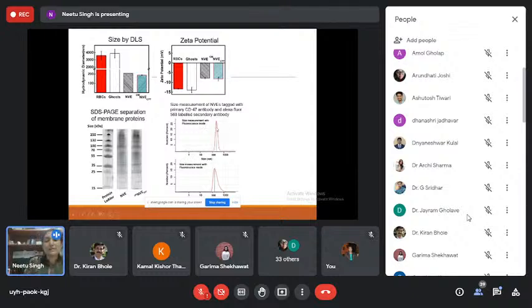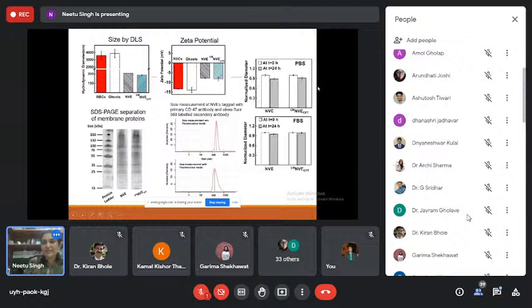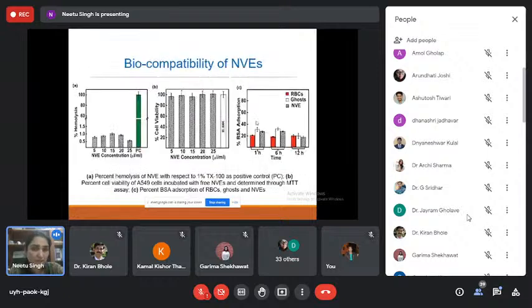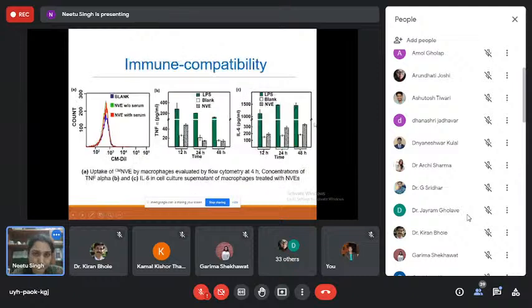So we started looking at whether the particle size matches with your CD47 presence. We had this experiment, which was very interesting. We had an antibody against it, and we tracked every single particle. As you can see, they all have the CD47 on them. We did some experiments looking at protein adsorption, and they had less protein adsorption, similar to what we have in RBCs. We studied the biocompatibility, and of course, this is more important. They were very biocompatible, and you had similar protein adsorption compared to RBCs and the ghost, even after 12 hours, okay?